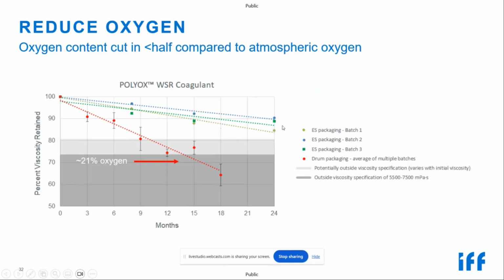But I wanted to give you a little glimpse into why we're so excited about this packaging, because when we use this, we significantly slow down the auto oxidation rate compared to the fiber drums. The fiber drums data, an average of several batches, is this red dotted line, and you can see the viscosity loss over time. This gray area is the theoretical zone of potentially these batches going outside the viscosity specification. This dark gray means definitely they're out of specification. The reason we have the bars is because each batch starts at a different starting viscosity, so they have a different percent viscosity retained where they're going to fall out of the specification.